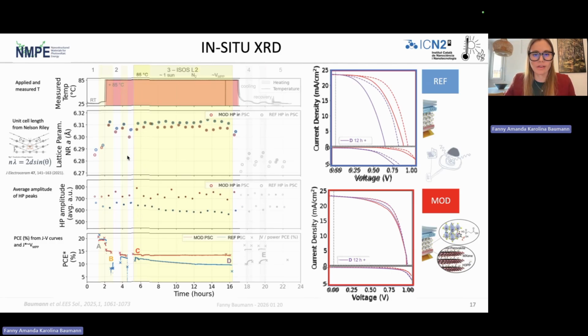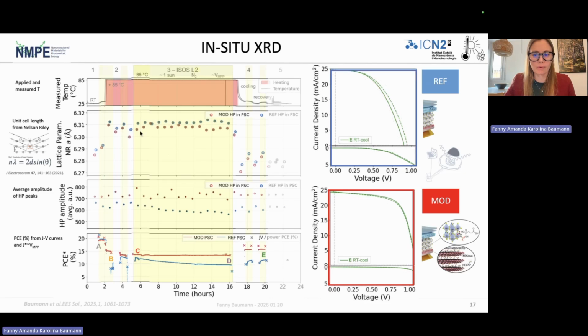And I will bring your attention to that more, but the only thing, as you can see, is that there's a small decrease in the intensity of the halide perovskite peaks in the reference, and also there's a continuous decrease in the efficiency of the device. Furthermore, we cooled the device, and we also did some testing to see what temperatures our holder reaches when we do light on and off, and we also tried to see if heating the device to a similar temperature would produce a similar change, which we saw that it did not.